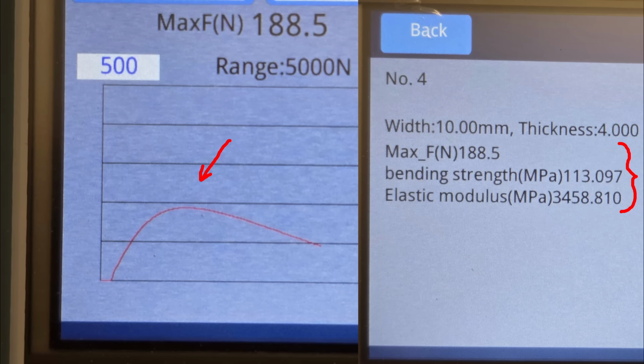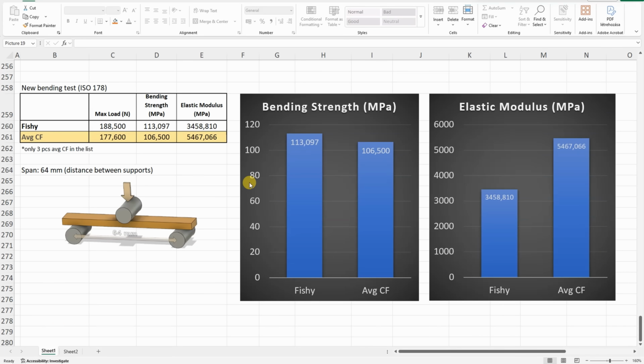Here you can see the graph in function of time or deformation, bending strength and elastic modulus. Another test which I started recently, and I don't have enough data. I have only 3 carbon fiber reinforced filaments in that list where I have these numbers, and I will use them for the comparison. The maximal load and the bending strength is quite good for the fishy filament. Elastic modulus not really, maybe this is typical for the nylons, since they are more flexible.